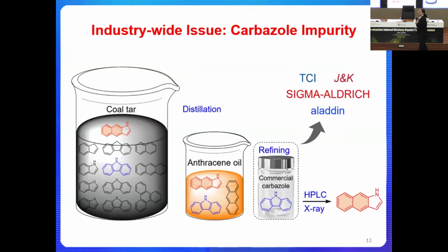Now, if we look into the literature, or if you look into our common practice, this problem is not casual. All the commercially available carbazole actually has this impurity. And this diagram shows how the commercial carbazole molecule is produced. It goes through the coal tar and then distillation and refinement, and then you get commercial carbazole with purity from 95% to 99.99 whatever percent. But nonetheless, for many of these commercially available molecules, we will be able to identify this isomer as one of the impurities, not all, right?